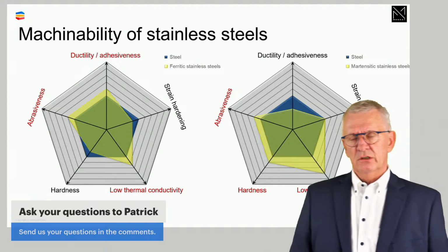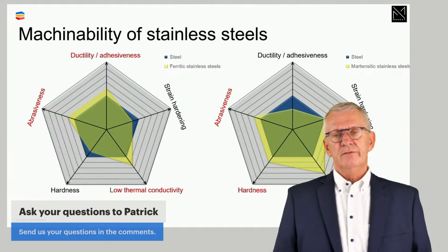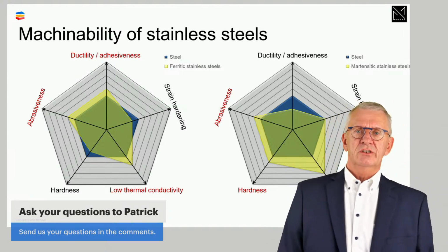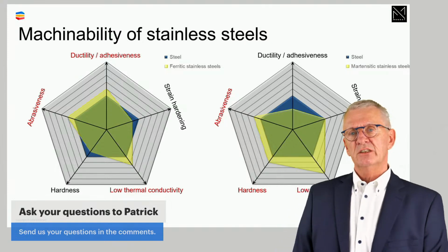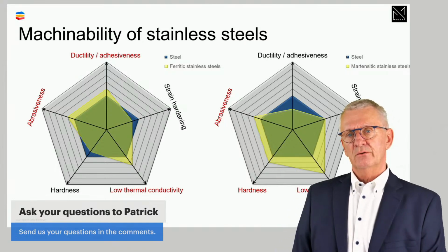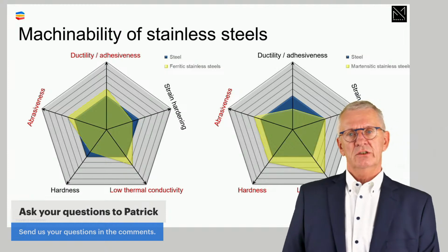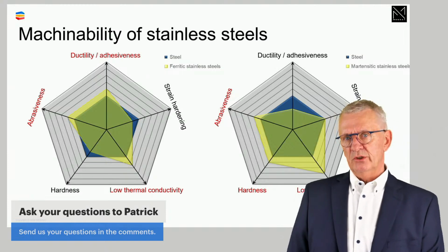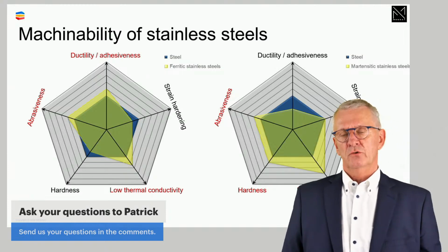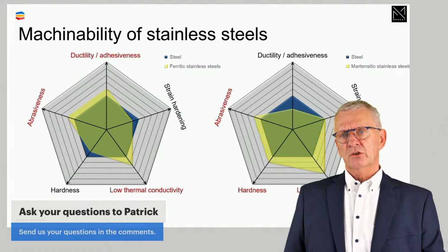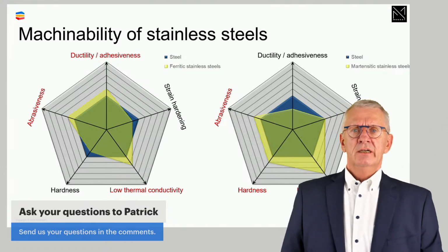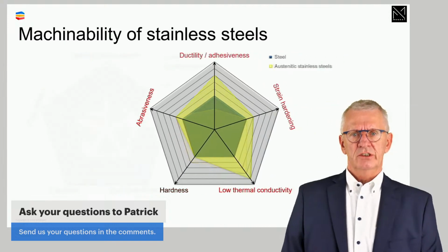That means that we have to be careful with the heat which is generated, because if more heat is generated, it's not that easy to evacuate it away from the cutting zone as it is in traditional steel, meaning that the cutting temperature will go up higher than what we are used to. And that has consequences. That has consequences for tool selection. That has consequences for cutting condition selection.